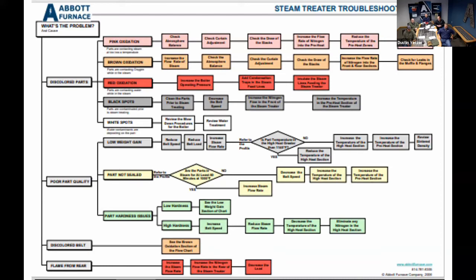Then we talk a little bit about part quality. There's typically two reasons people steam treat. One is to add a rust preventative coating. Rather than red rust, we're creating an Fe3O4 blue rust that's quite stable. The other reason is a little bit of hardness for a wear surface, or they're steam treating to seal the porosity in a fluid powered component, whether it's a pump or a shock absorber, where you don't want the fluid to be able to penetrate the porosity in the part.